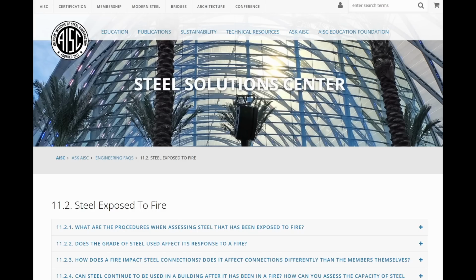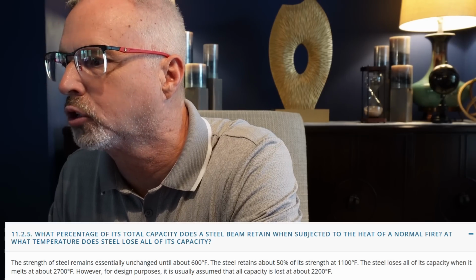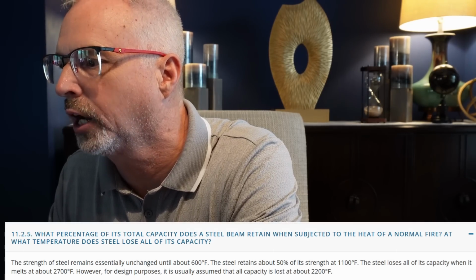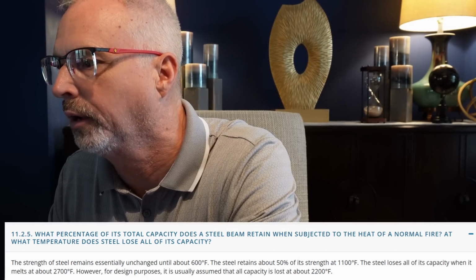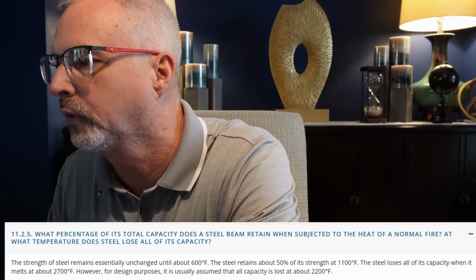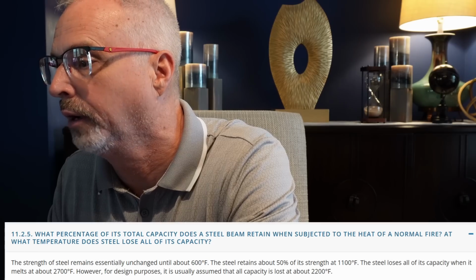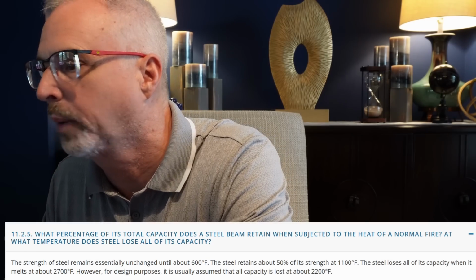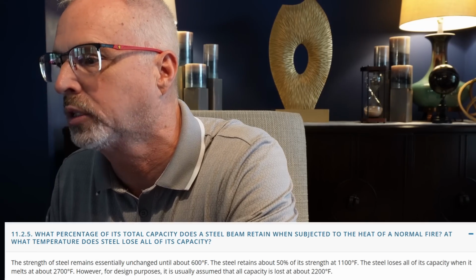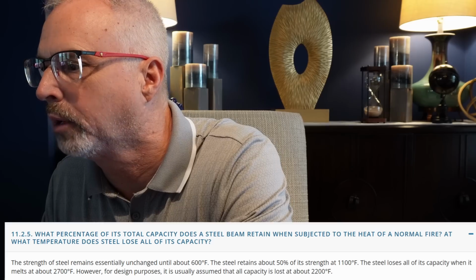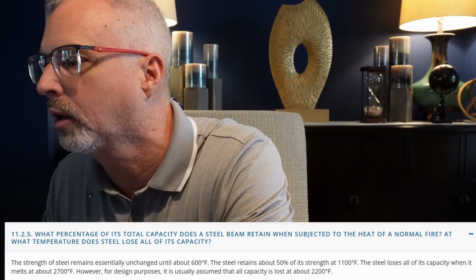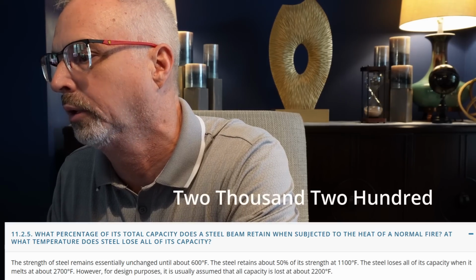Now let's get into the steel aspects of this. There's an excellent reference site here from the American Institute of Steel Construction, and they have some facts on steel exposed to fire. This is one of the things I want to touch on here. The strength of steel remains essentially unchanged until about 600 degrees Fahrenheit. The steel retains about 50% of its strength at 1100 degrees Fahrenheit. The steel loses all of its capacity when it melts at about 2700 degrees Fahrenheit. For design purposes, it is usually assumed that all capacity is lost around 2200 degrees Fahrenheit.